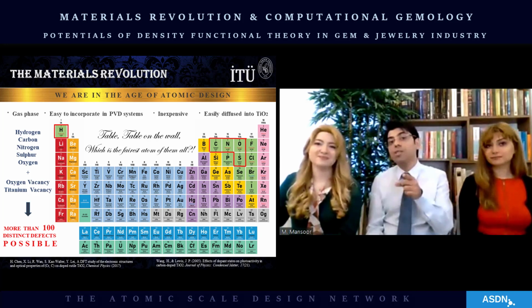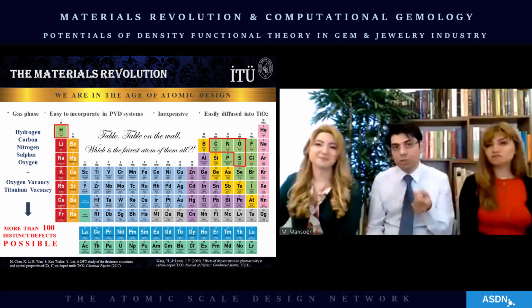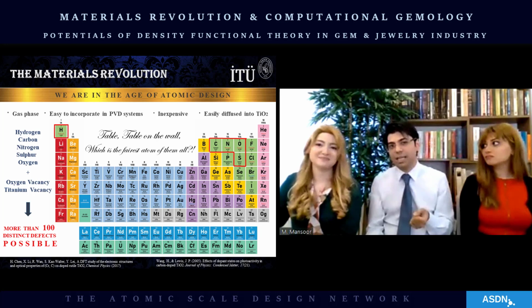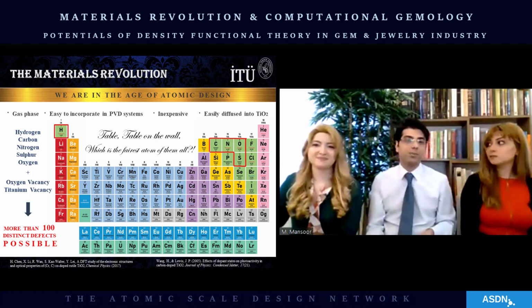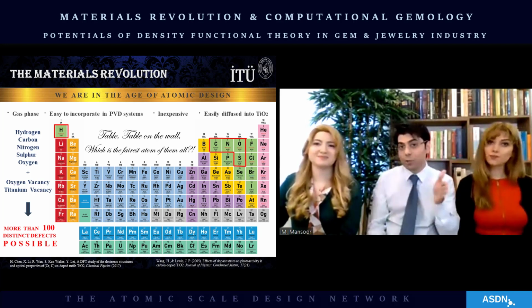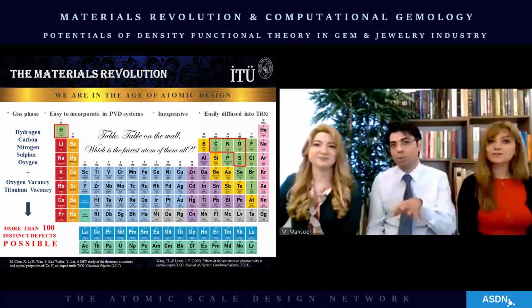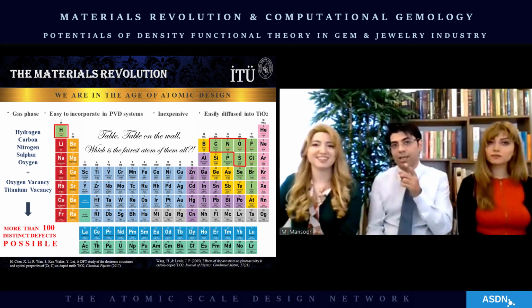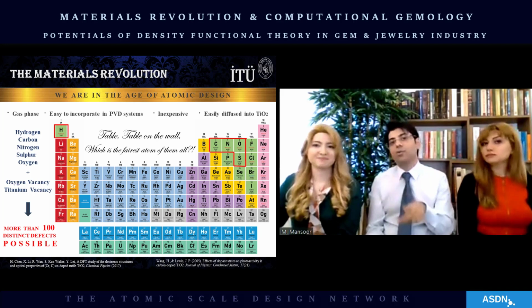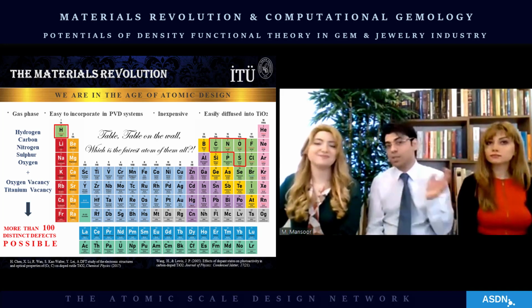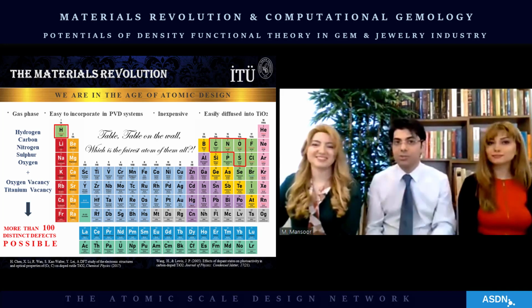In fact, carbon seems to be offering great potential as well. So a study by Professor Lee's group back in 2017 has shown that carbon, which is positioned on the oxygen site, can reduce the effective band gap to 2.74 electron volts, with the new allowed states very close to the valence band, resulting in absorption of the blue light to some extent. And there's also another interesting work by Wang, which has reported experimentally that carbon-doped rutile has caused a redshift in the absorption spectra and an increase in the photocatalytic activity. So we thought, well, this is interesting. We're on the right track.